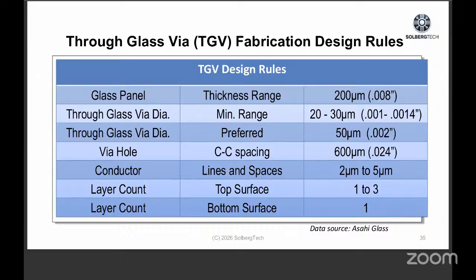The design rules are in flux somewhat, and I have some figures here. They may change, and it depends a lot on the individual company's capabilities. So we look at the through glass via diameter. I have 20 to 30 microns per hole diameter. But a lot of companies are looking to be more producible, so they may go to a slightly larger size if possible.